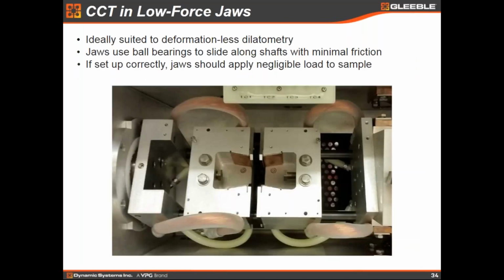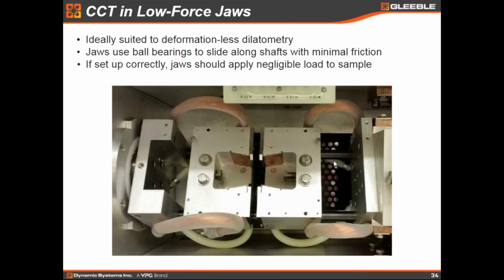But the low force jaws are really what's meant for dilatometry work. They do a very good job with that. The jaws themselves, as most of you probably know, have a ball bearing system that slides along those black shafts back here, and so they slide through with minimal friction. If set up correctly, there should be negligible load in your sample with these. So it's a pretty good option for dilatometry.